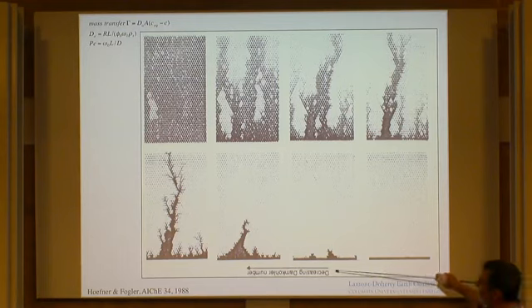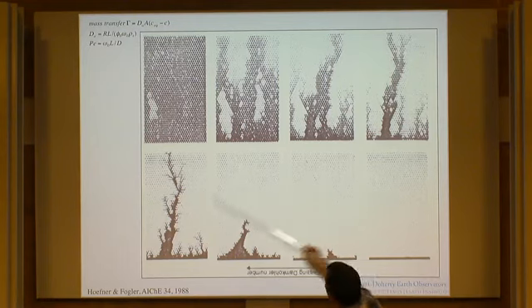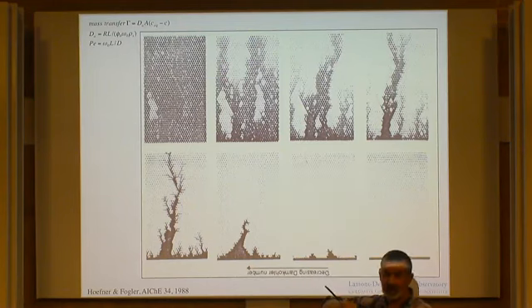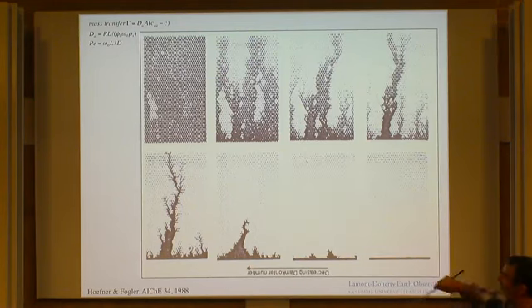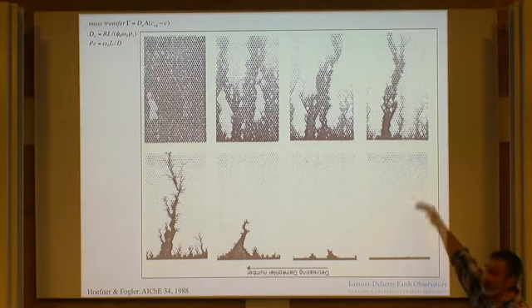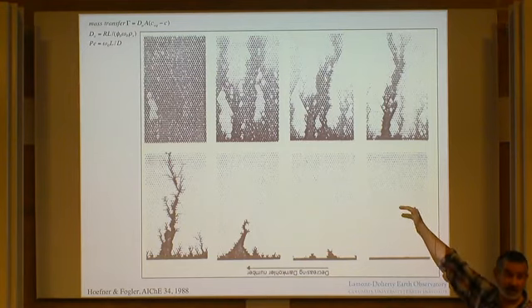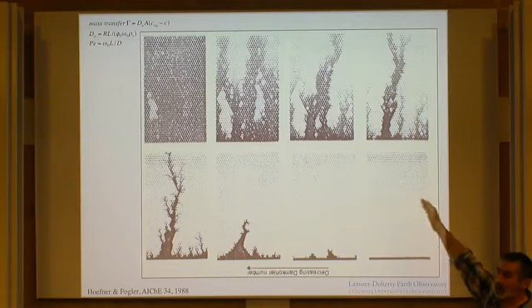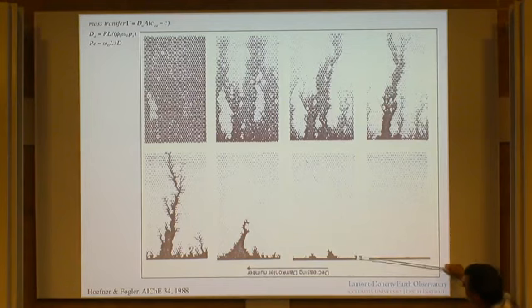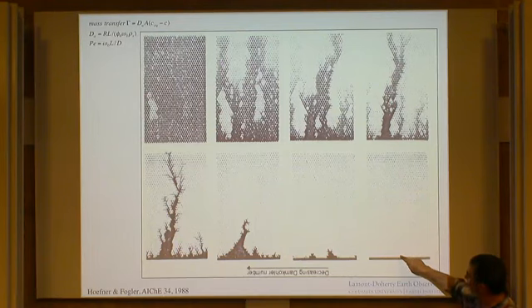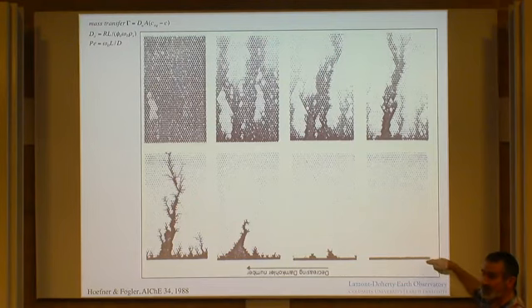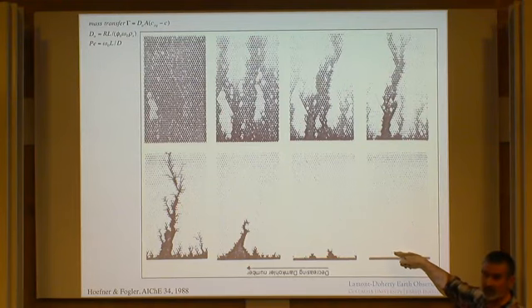And they say that these are going in order of decreasing Damköhler number, which sounds very fancy, but really what they're doing is varying the pressure gradient that's driving flow through this model and leaving everything else constant. Okay, so really slow flow velocities. There are perturbations in the porosity and permeability here, but they don't grow into channels because chemical diffusion across the fingers is enough to homogenize the soluble phase concentration. So there's no advantage to being in the finger.